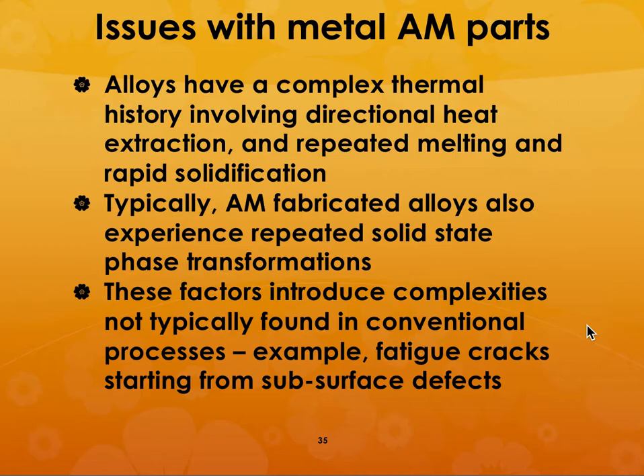The other thing is that because you are going to have melting and rapid solidification on the surface, if you are going to be making this under an inert gas, that inert gas can easily be absorbed or adsorbed by the molten metal pool. That molten metal pool can create subsurface defects, which in turn can affect fatigue properties, because those fatigue cracks can start from those points rather than from the component that is made by additive manufacturing.